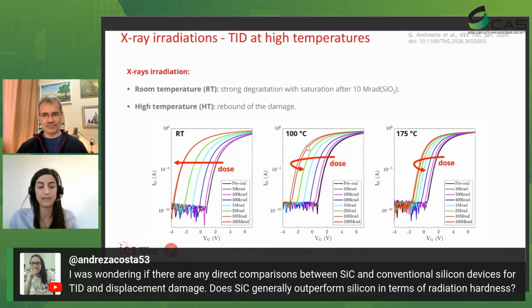So in that sense, silicon is better than silicon carbide. However, it also depends a lot on the thickness of your gate oxide. A thicker gate oxide, as sometimes you might find in some silicon power components, might trap more charges, and so you might have a larger degradation of your threshold voltage, which is what we are observing in an experiment we are currently doing. So for TID, it depends a bit on the architecture as well. There are a lot of different trench architectures for silicon with respect to silicon carbide, so that can also have an impact.